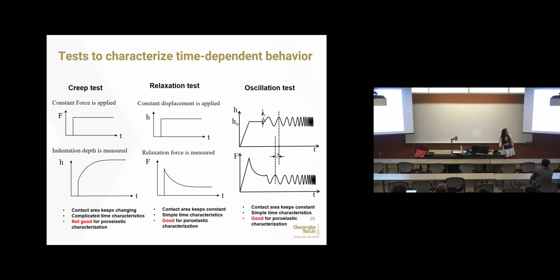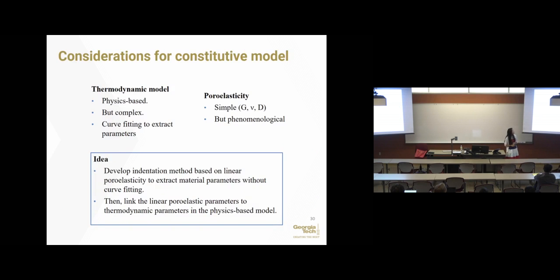So with that in mind, we realized the relaxation test is better. You keep a constant indentation depth and measure the force as a function of time. So the contact area does not change, and the characteristic time does not change. It's more possible to get a clean solution out of it. And the oscillation test is also good, but you have to apply a trick here. You have to apply a big indentation depth in the beginning, so you generate a big contact area, but the subsequent oscillation is in small amplitude, so the contact radius change during that time can be neglected. I will talk about that.